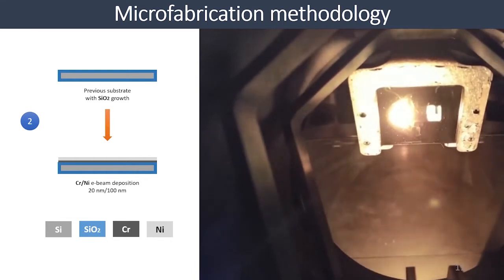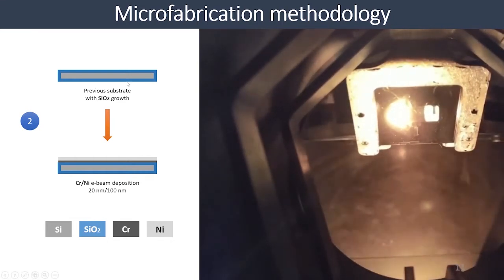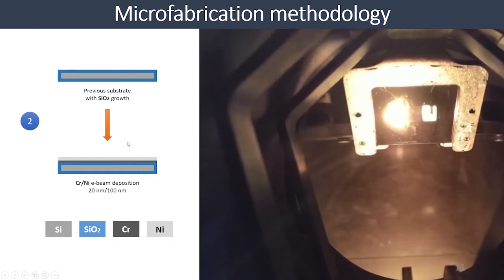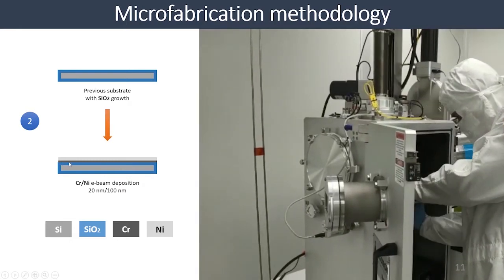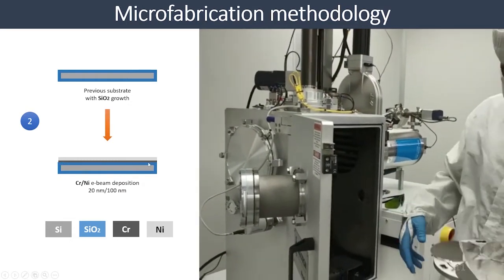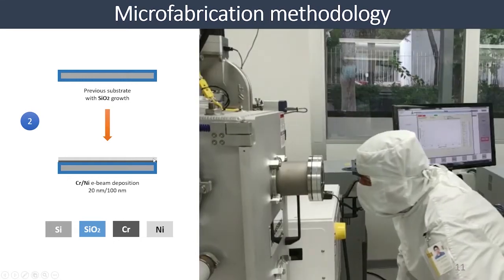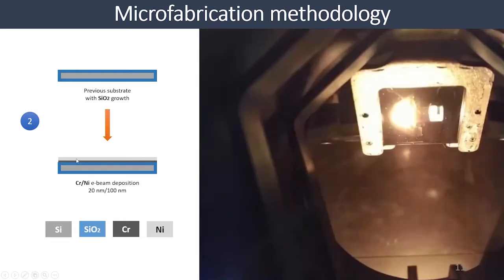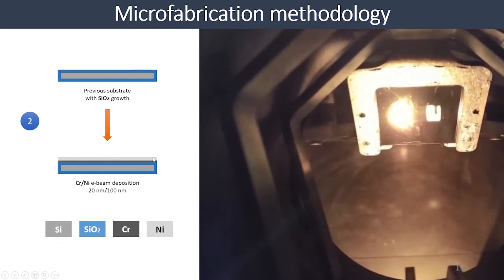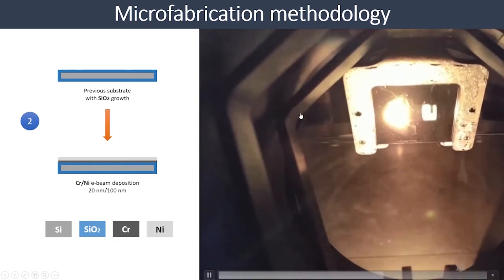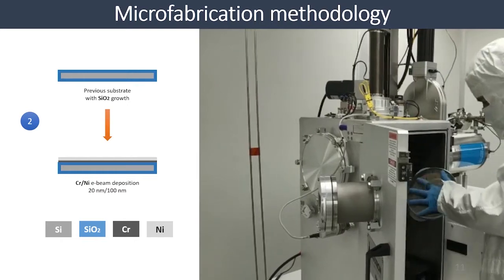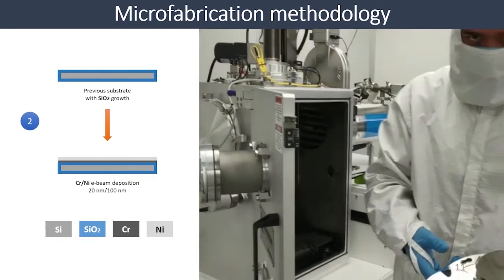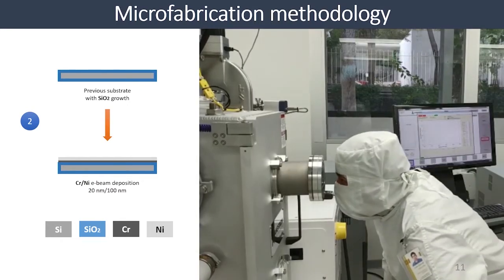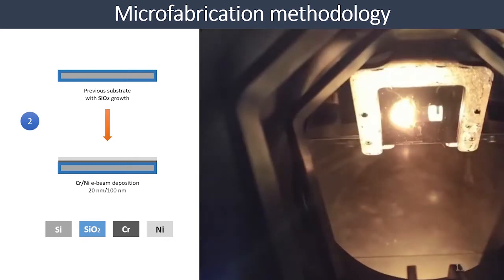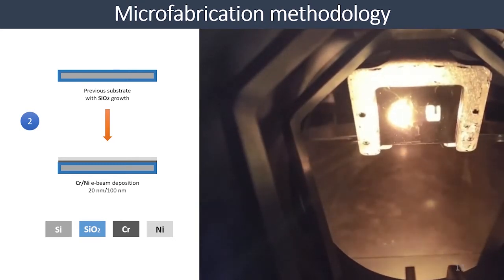So we start with the previous substrate with silicon oxide, and then in a single process, we deposit 20 nanometers of chrome that functions as the adhesive layer for the 100 nanometers of nickel that is going to be the material of the sensor. There are some important things to mention here. The first one is that the e-beam system that we use is adapted for only one wafer per deposit, but to increase the production, we place 3 wafers for each deposit, as we can see in the video.